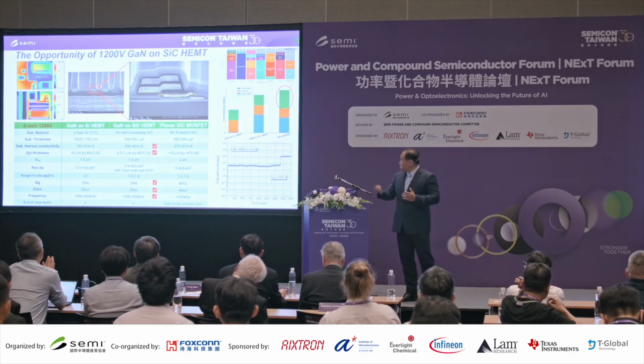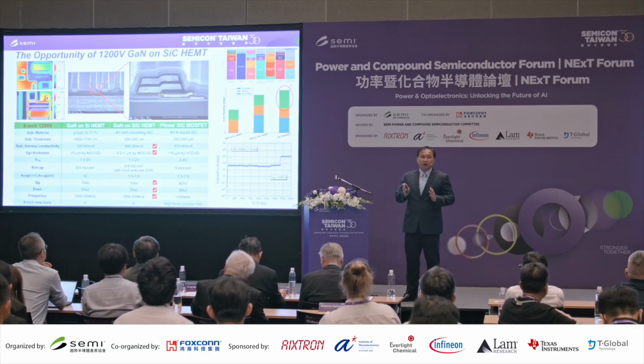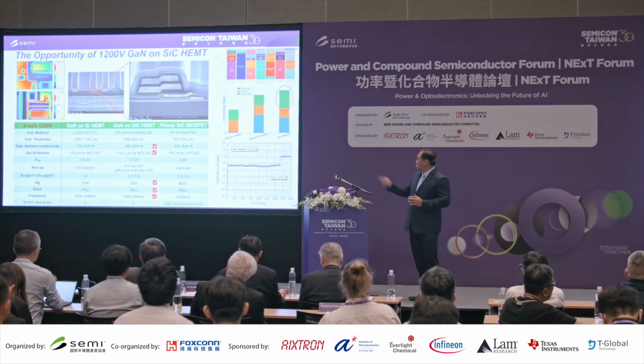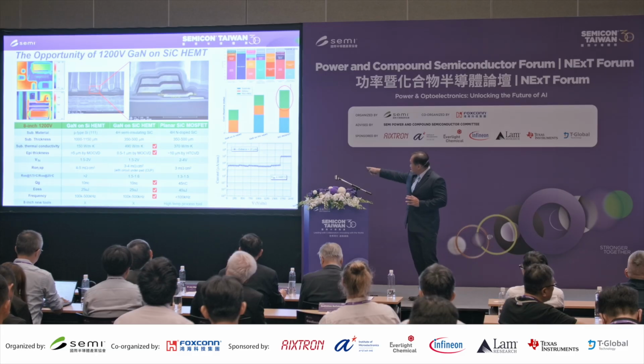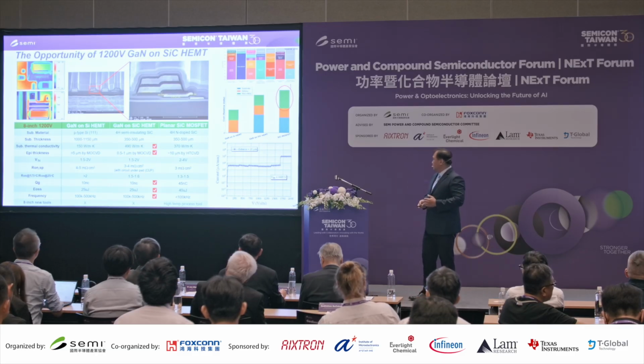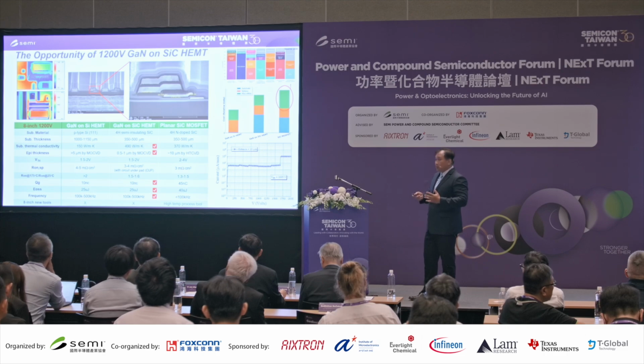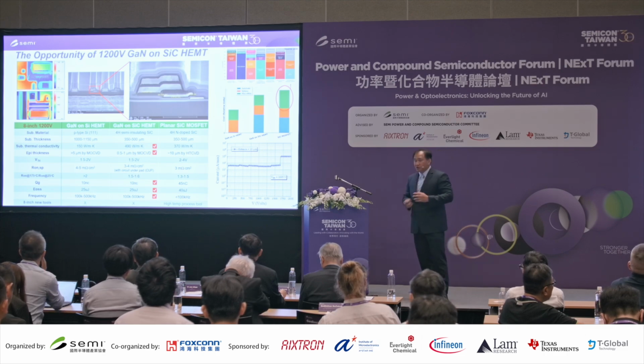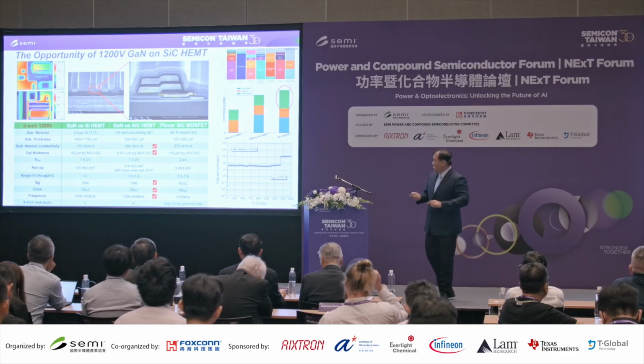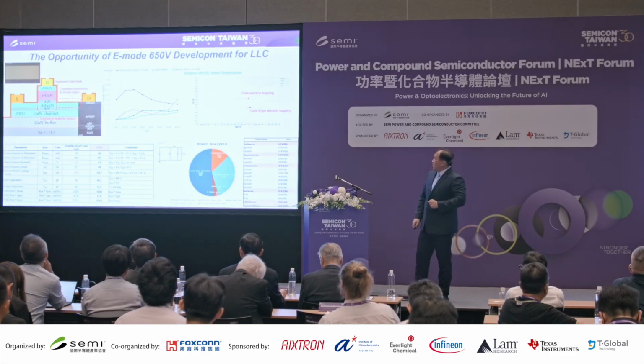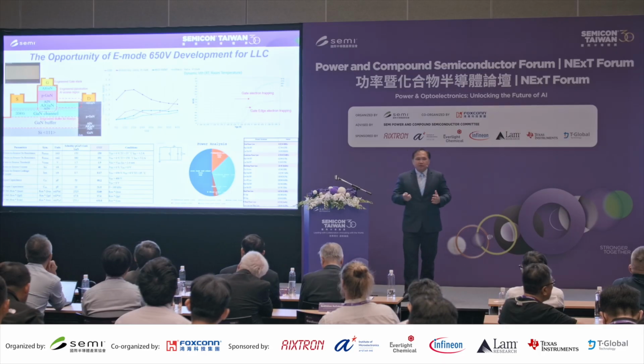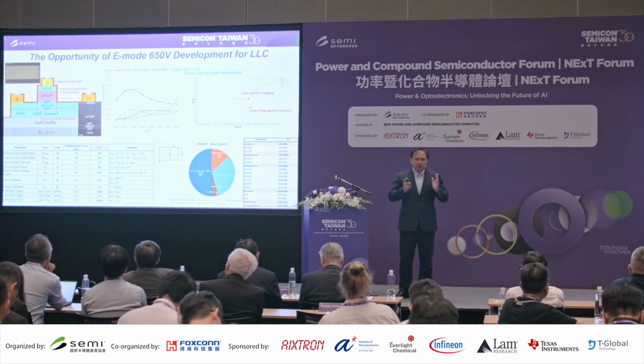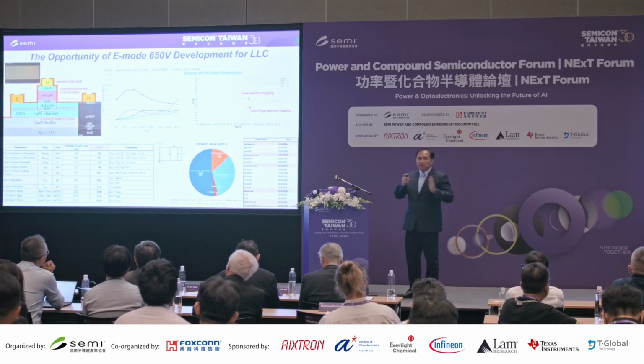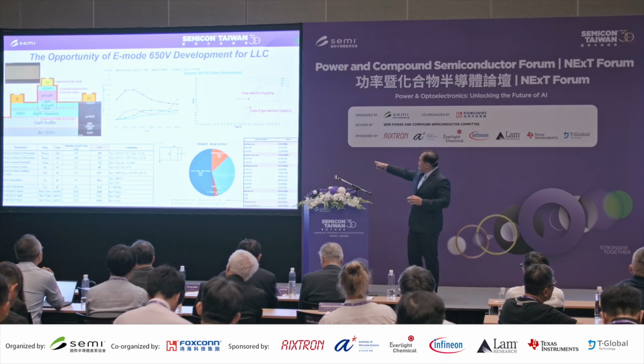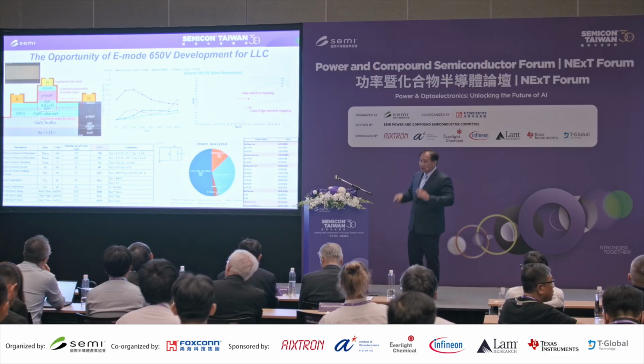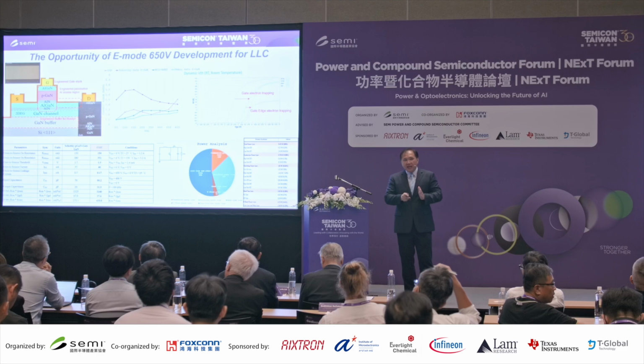But if you eventually use the GaN silicon carbide HEMT technology, you don't have to add the high temperature equipment. And of course, the breakdown voltage, silicon carbide is very good for the breakdown voltage. Actually, the breakdown voltage was dominated by the back end of the line on the gallium nitride surface. Okay, so another opportunity I just mentioned is for the E-mode 650 volt. The device improvement should depend on the different application, and you have to measure the different power loss and the partition, which is the device getting, and then do the improvement.